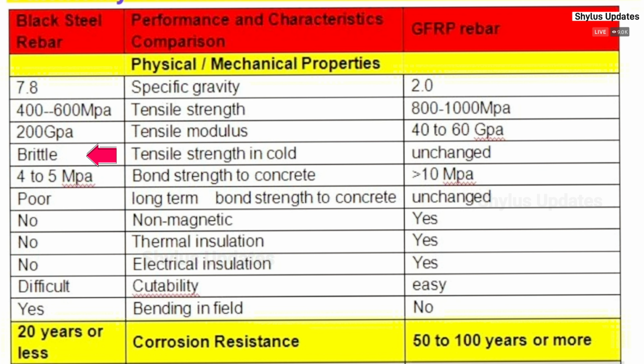Tensile strength in cold for steel bar is brittle. Tensile strength in cold for GFRP bar is unchanged. Bond strength to concrete for steel bar is 4 to 5 MPa. Bond strength to concrete for GFRP bar is greater than 10 MPa. Long-term bond strength to concrete for steel bar is poor. Long-term bond strength to concrete for GFRP bar is unchanged.